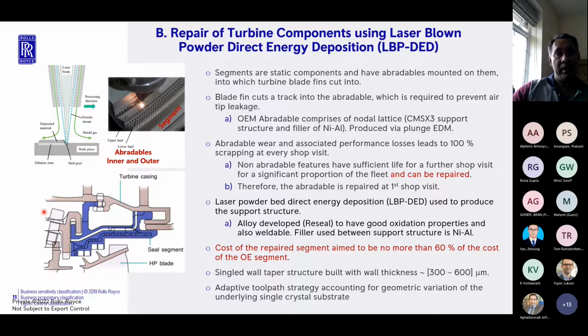So typically the cost of this entire repair process is aimed to be less than 60% of the cost of the OE segment. So automatically you've got massive cost saving. So this is an example. You've got a segment here. You use a nozzle to deposit powder through the nozzle, and you've built up this support structure. So clearly you see the support structure has been built up already on this surface, and it's in the midst of being built up on that surface. So this part of the surface has not yet been built.